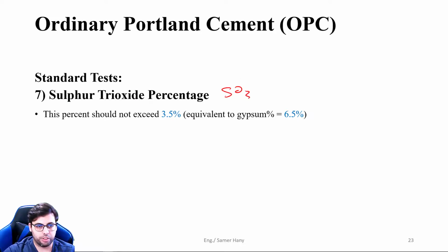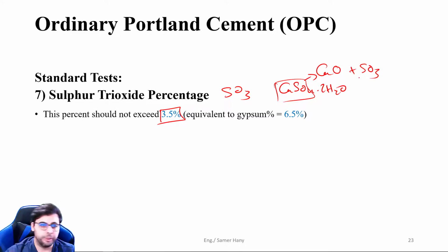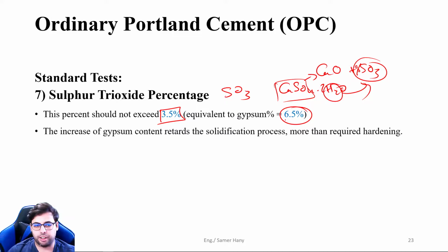The 7th and last standard test for the quality control or assurance is the percent of sulfur trioxide. This should not exceed 3.5% of the total mix. And this sulfur trioxide, where does it come from? It comes from the calcium sulfate, right? Calcium sulfate, or the gypsum we added. When analyzing this, it will be broken down into calcium oxide plus sulfur trioxide. Okay? And of course, the water vapor will evaporate. So, the percent of sulfur trioxide given by the analysis should not exceed 3.5%, which is equivalent to 6.5% gypsum. Any more than that means that we've added too much gypsum, and the solidification process or reaction will be too slow for the application. Okay?